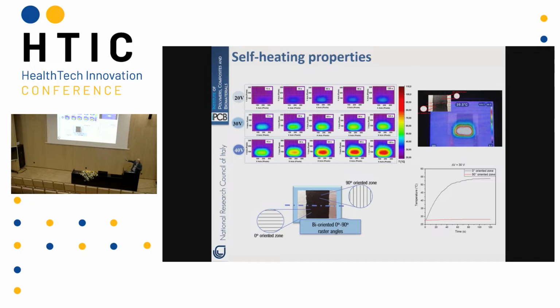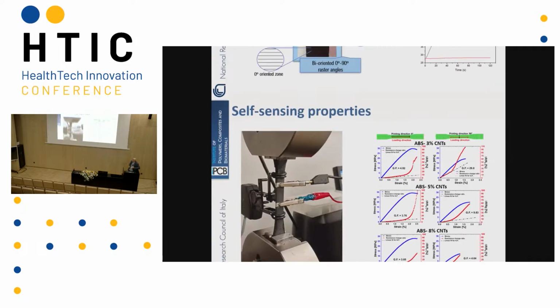So it means that by applying the voltage, you obtain an increase in temperature in just one side of your sample. Of course, over time the heat diffuses by thermal effect, but that is not due to the generation of the heating, which applies just on one side. It means that if you are able to design your object, making the right direction of printing in the different zones, you can regulate the temperature inside your object, just doing this and using the same material for the whole object.